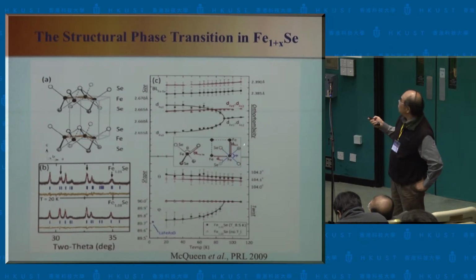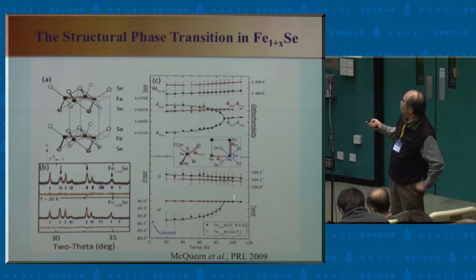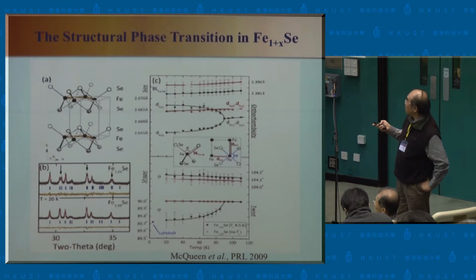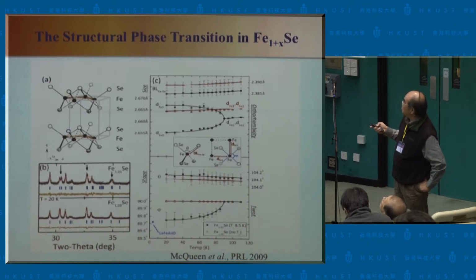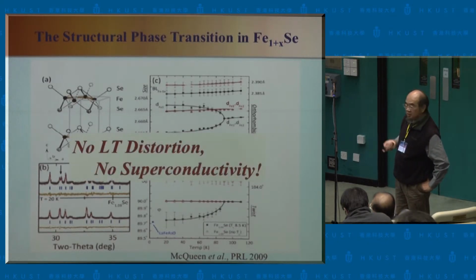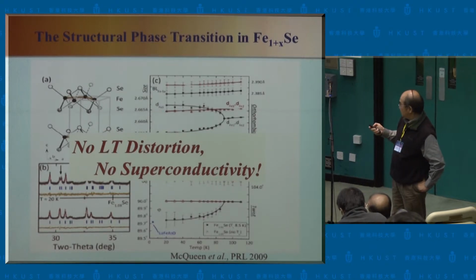Okay? If you don't see, this is the result from Cava. By using different compositions, they see that for a superconducting one there is a distortion, while for a non-superconducting material, with a higher iron content in their composition, around 1.03 or something like that, the iron-rich one that is non-superconducting, the distortion disappears. So the conclusion is this: the low temperature distortion has correlation; no distortion, no superconductivity.